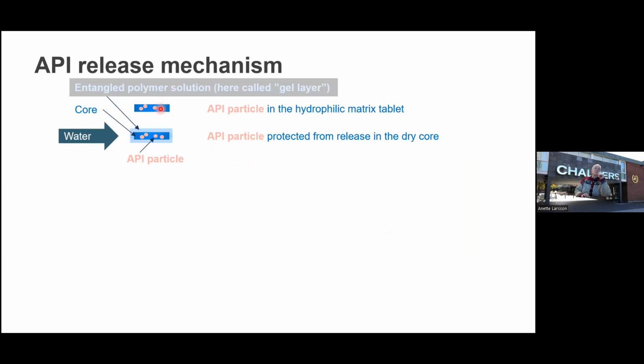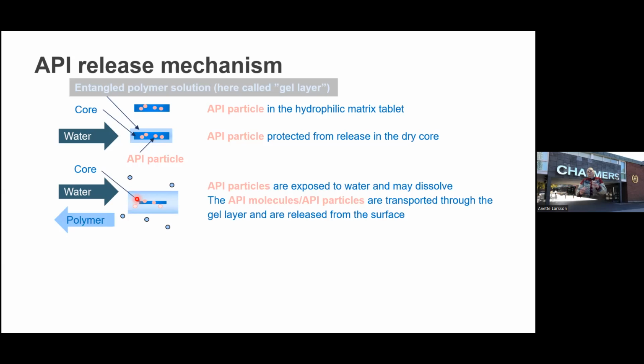So here we have the drug particles embedded in the core, and we put them in water. We get this gel layer formation, but the API particles here are protected in the dry core because the API particles can't dissolve if there is no water there. But finally, the core diminishes and we get API particles out in the gel layer, and then two things can happen. They may dissolve or they may not dissolve. So they may stay as particles. And the funny thing is that both the dissolved API molecules and the API particles can be transported through the gel layer, and that I will tell you a little bit more about very soon.